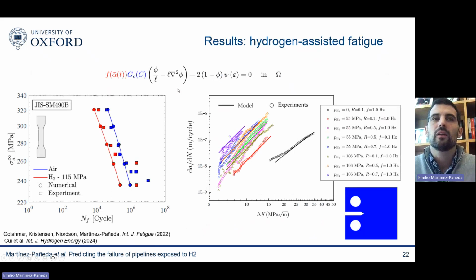So that's reassuring. And one last thing that I want to say is that the model also works very nicely for fatigue. And you can see here that, again, we have a fatigue degradation function. There's no additional coupling defined between the fatigue and the hydrogen. It's just that both degrade the fracture energy. So there's no extra fitting parameters. And you can see that by doing that, we're able to get a very good agreement with virtual S-N curves, but also a very good agreement with fatigue crack growth rates.